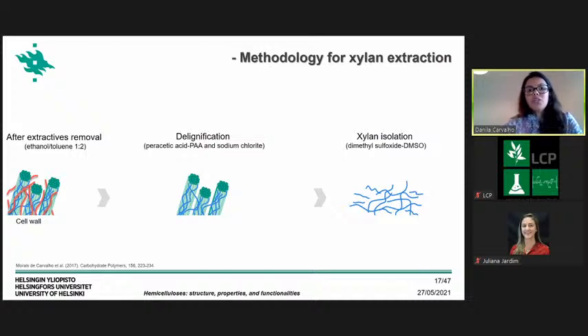Other important things to be considered are the methodology used for the extraction of the material. In this case, what I was applying was removing extractives first from the biomass. Then after removing these extractives, I was applying two different delignification methods. One of them using peracetic acid and the other, sodium chlorite. And then I was solubilizing the xylan in a solvent. In this case, I was using dimethyl sulfoxide. And using this protocol, I could at the end get the xylan with the acetyl groups preserved.